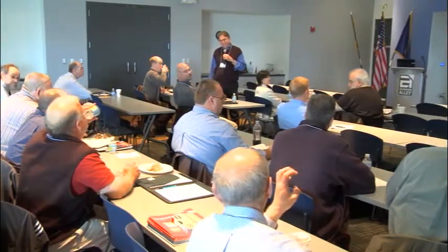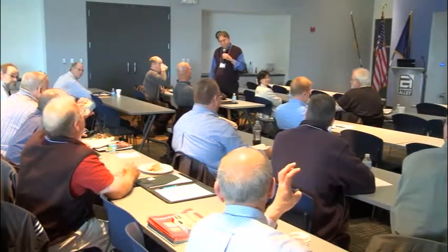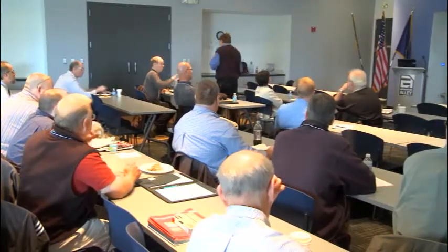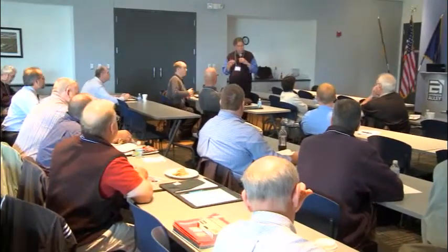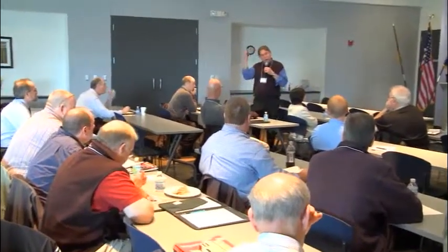Please don't do unpainted metal, folks. The only time you can do that is in die casting. There's a patina built up on a die cast mold, the injection mold, from all the lubricant. It's charring and a patina, and it's a good emitter. 0.92, 89 to 92. When I shoot die casting, I do about a 50 spot measurement of emissivity. I take an average emissivity, and then I avoid any flat, shiny areas. I don't even want to go there on a die casting. But injection molding, look at the part every time. You're not going to see it, unless there's geometric reasons.